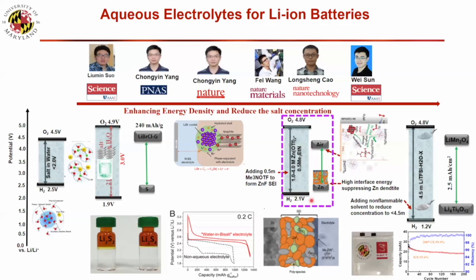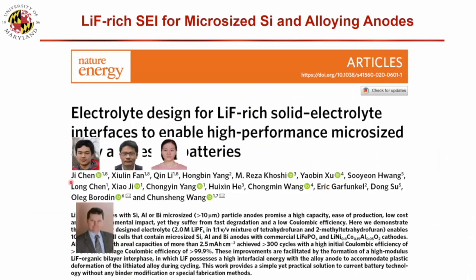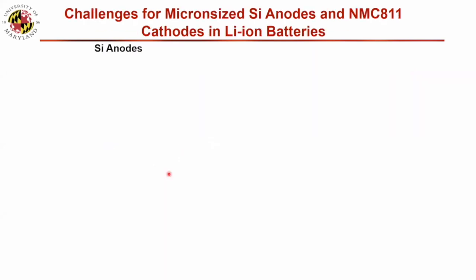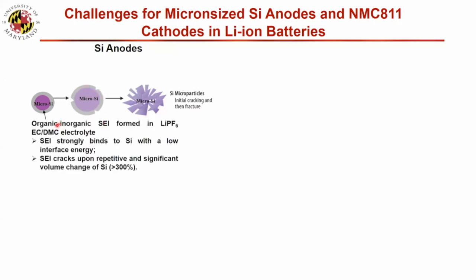So today I will take this as an example to show the chemistry and the principle, how the interface energy can prevent zinc dendrites. First, let's talk about the lithium-ion battery, where we use silicon. For a micro-size silicon anode, the silicon cracks, and the SEI also cracks. The reason, as we just mentioned, is that the SEI is strongly bonded with silicon. Silicon cracks, so the SEI definitely will crack. If the SEI cracks, electrolyte penetrates, and then the silicon particles are separated from each other, and we lose capacity.